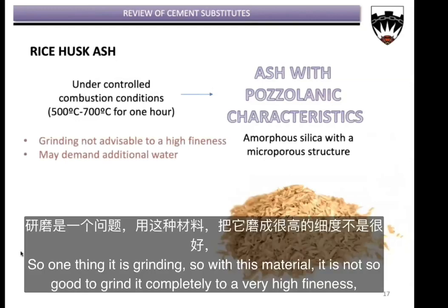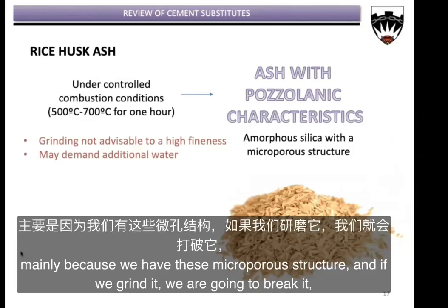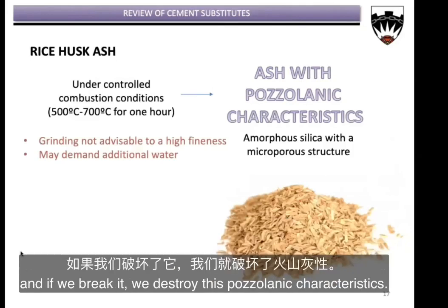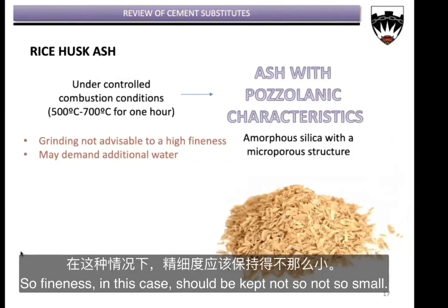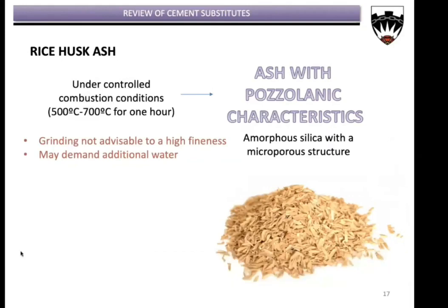So one thing is grinding. With this material, it is not so good to grind it completely to a very high fineness, mainly because we have this microporous structure, and if we grind it, we are going to break it. And if we break it, we destroy these pozzolanic characteristics. So fineness in this case should be kept not so small, okay?